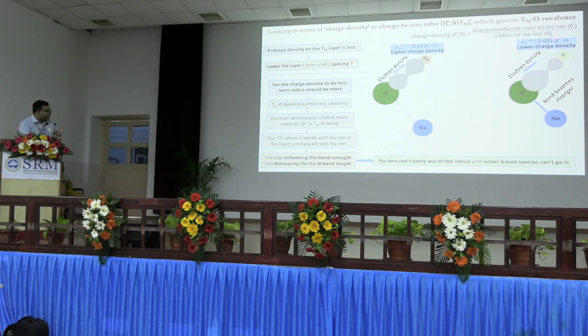We can do that by tuning the composition of my transition metal layer, to make the overall electronegativity of the transition metal oxygen slab go down. So to make the covalency of the transition metal oxygen slab go down, so that I can have a greater effective negative charge on the oxygen ion, this being more ionic and less covalent, and I can have a strong sodium oxygen bond.